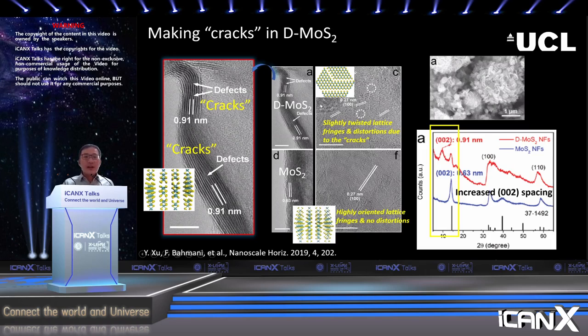Not only are we able to create defects in the molybdenum sulfide, we also utilize these defects to increase the interlayer space, which can be verified by the XRD patterns, where the 002 peak shifts to the lower angle position, which means the interlayer space of molybdenum sulfide is increased from 0.63 nanometers to 0.91 nanometers.